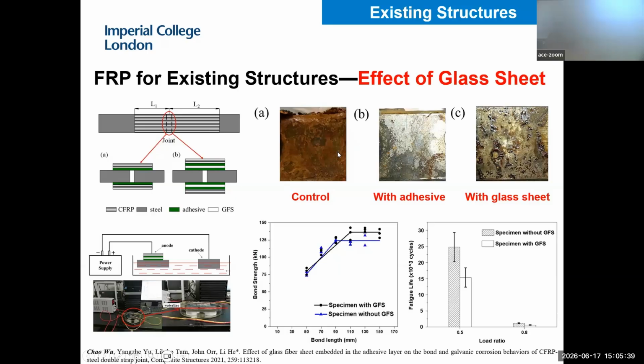So in practice, it's proposed that before you bond carbon fiber onto the steel plate, you introduce a layer of glass fiber fabric in the adhesive, so the glass fiber separates the carbon fiber and steel plate. Then they don't contact each other, so there is no issue of galvanic corrosion. However, nobody has answered how introducing a layer of glass fiber will affect the bond, because the bond is a critical linkage—if you don't have the bond, you don't have a strengthening effect.